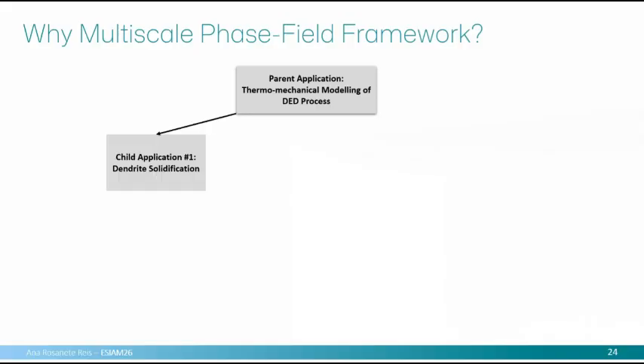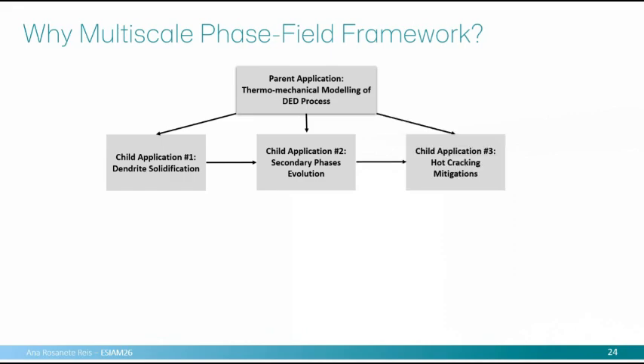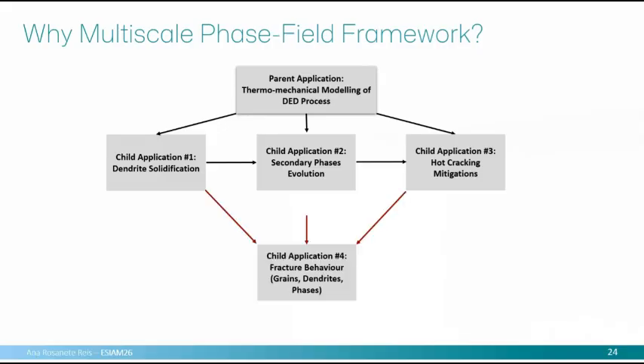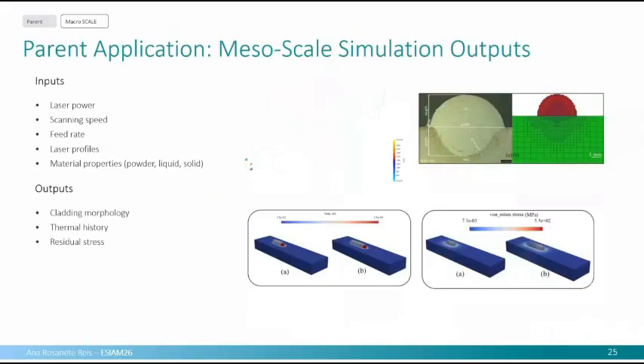where you go from thermomechanical modeling, so macro scale modeling, and then you go to dendrite solidification, and secondary phases, which in the case of Inconel is very important, and then predicting hot cracking. And finally, if you can use everything like this, you can maybe achieve some indications for fracture behavior. So this was the numerical framework that we tried to develop. So dendrite, segregation, precipitation, and send some information about strength.